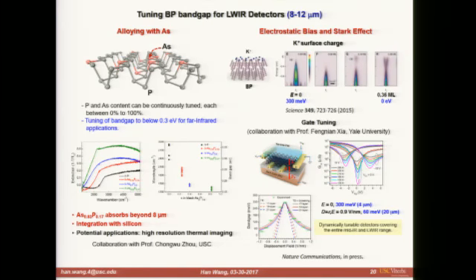These are not simulations—these are actual ARPES mapping of the band structure. The band gap basically narrows down and becomes sort of a Dirac cone kind of shape at a very high electric field. However, the doping-based method is not very attractive for device applications, for two reasons.